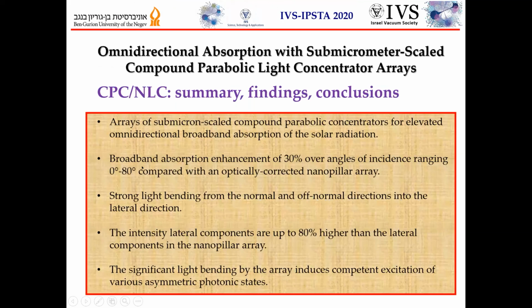Next, the conclusion. Arrays of sub-micron scale compound parabolic concentrators elevate omnidirectional broadband absorption of solar radiation. Broadband absorption enhancement of 30% throughout 0 to 80 degrees. Strong light bending in vertical cross sections. The broadband lateral component is 80% higher compared to the nanopillar array.